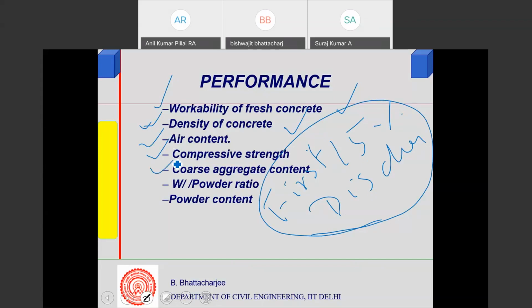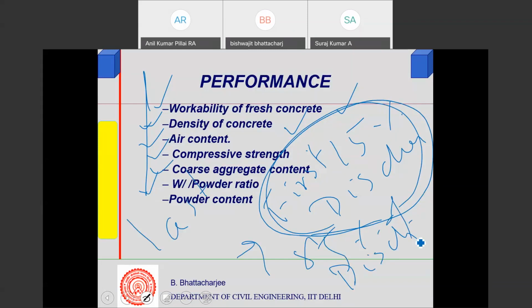For analysis of fresh concrete, it is sieved through a 4.75 mm sieve, and whatever is retained is the coarse aggregate content. Wet sieving through 2.36, whatever is the solid particle will be cement or powder. So there are ways. From the first 15% of the discharge and the last, that is after 85% of discharge, you again find out this.